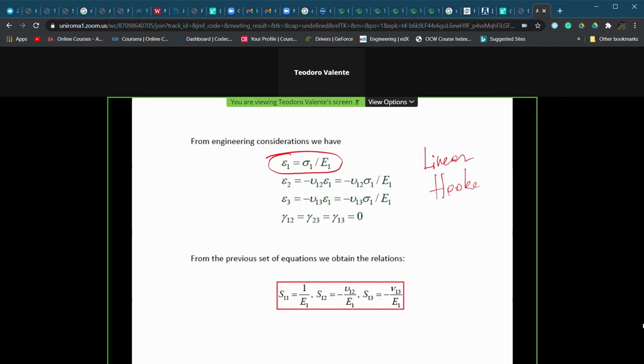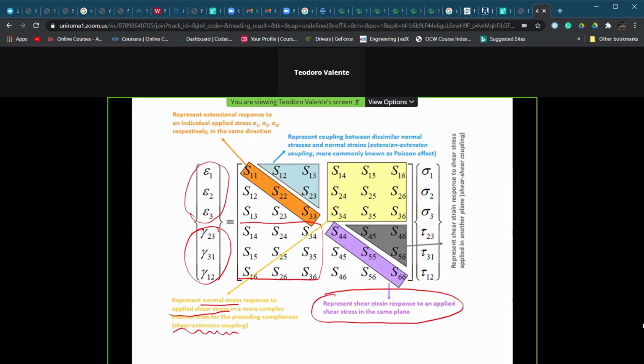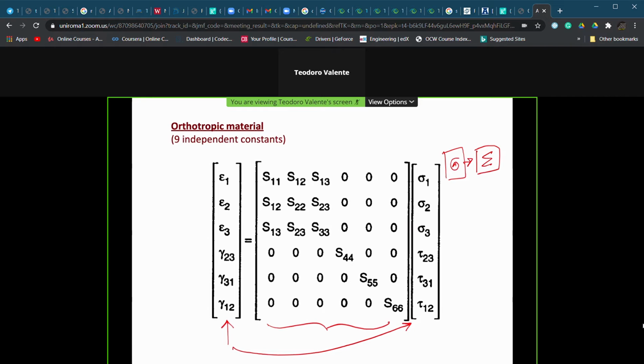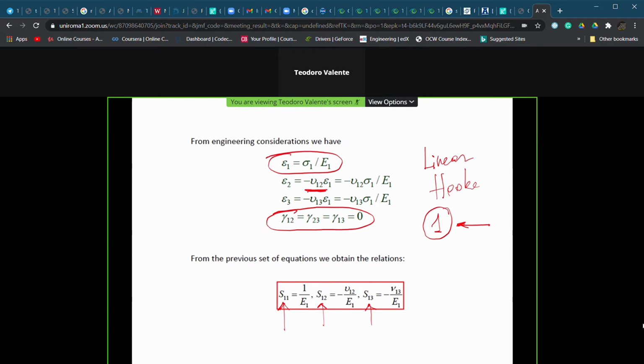If we remember the general expression for which the strain can be given by the stress divided by the Young modulus, and we remember also the meaning of the Poisson coefficient that we have just recalled, with this condition, because there is no shear in the case of a load applied in a uniaxial way in the 1 direction, we can derive, we can calculate the values of S11, S12, S13, which are values that we can put inside the compliance matrix. Let's take this general one, okay? Because we have seen that, again, here we do have, in our case, 0 values in many positions.